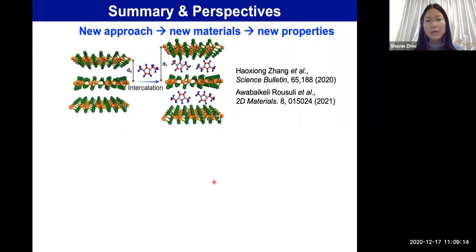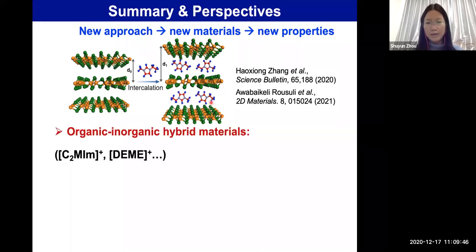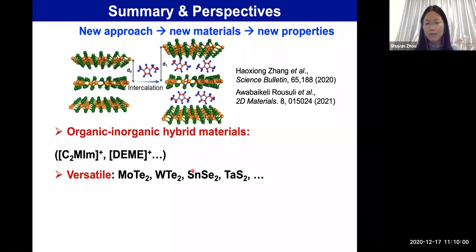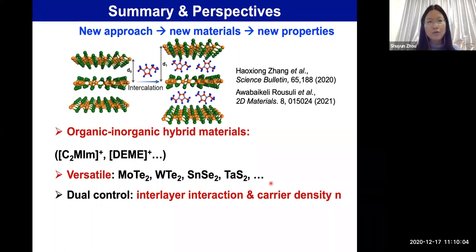So here is my summary. By using this new approach of this electrochemical reaction method, we can intercalate these large-size organic cations into the interlayer spacing in the layered materials. And through this intercalation method, we can obtain these hybrid materials with new properties. So this method actually is very nice. It applies to many different kinds of organic cations in the ionic liquid. It also applies to many different layered materials. And this intercalation method has a dual control. It not only controls the interlayer interaction, but also at the same time, it injects carrier densities into the materials.